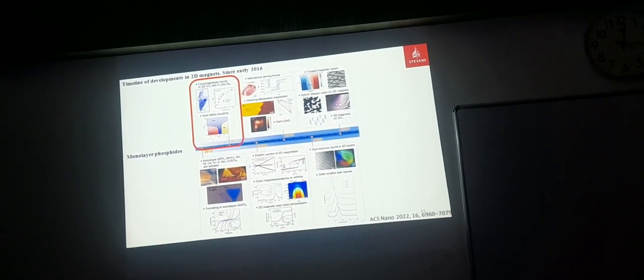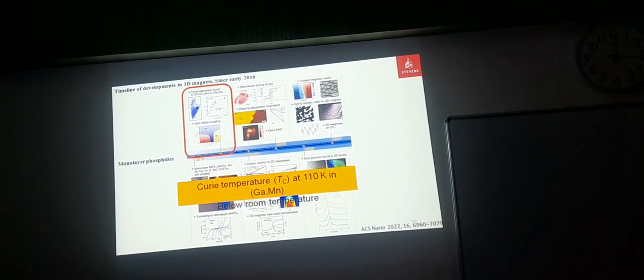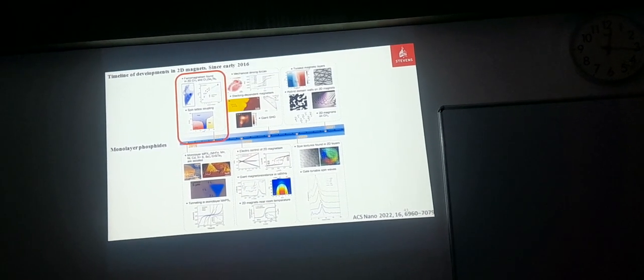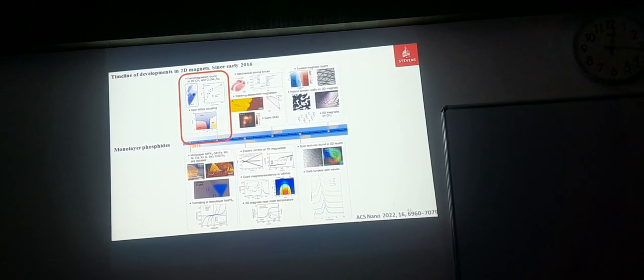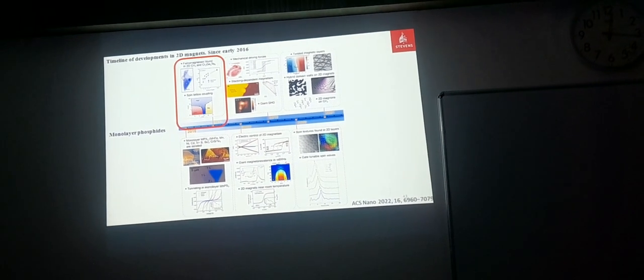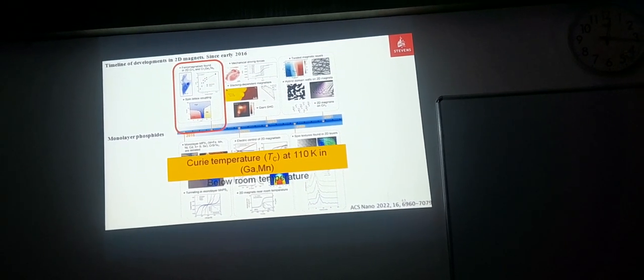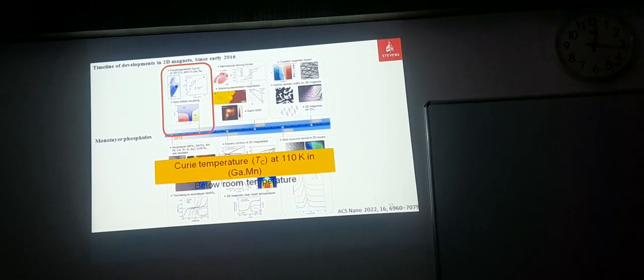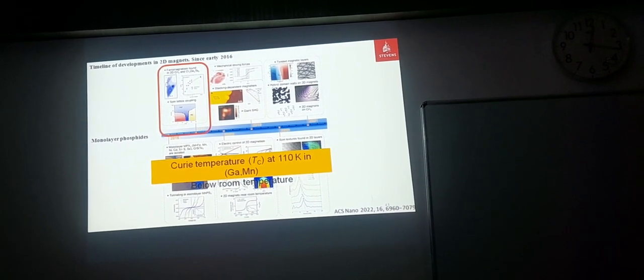There's a lot of research in the last couple of years, starting from 2016, and a lot of different materials have been developed. Most recently, chromium triiodide, one of the most important magnetic materials or quantum materials, has been developed. But the problem with these materials is that they are quite unstable. When exposed to the air environment, they immediately degrade. So then people looked at different two-dimensional materials. Not only that, the Curie temperature. If it is a magnetic material, it has a Curie temperature, right? If it is low temperature, that is not useful for real applications. A lot of people focused on how to increase this Curie temperature for real applications.